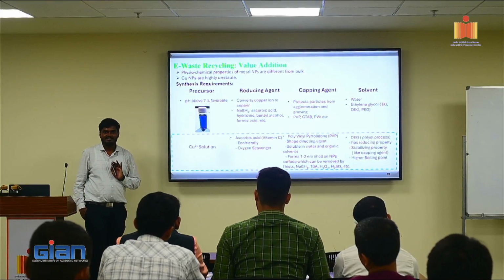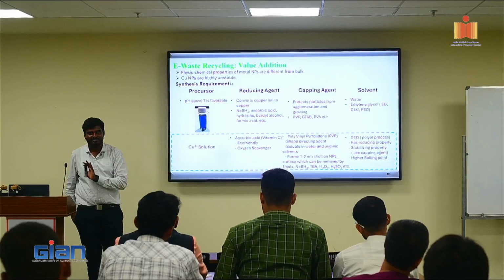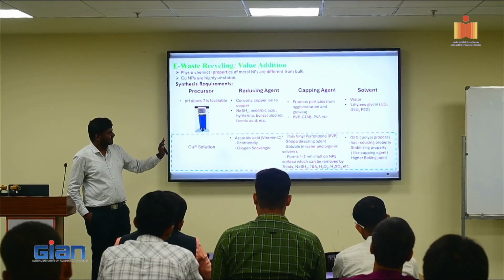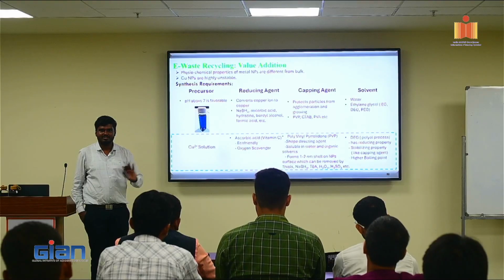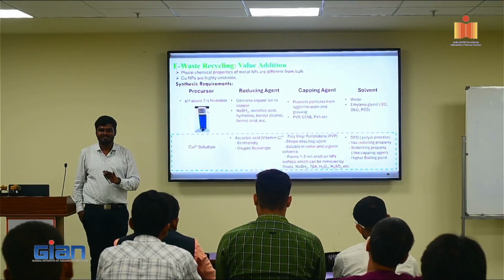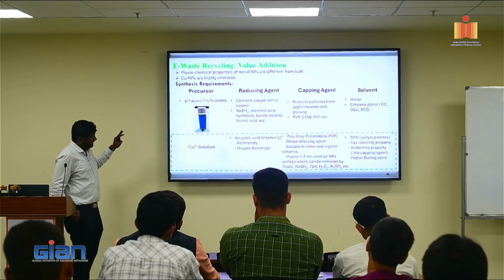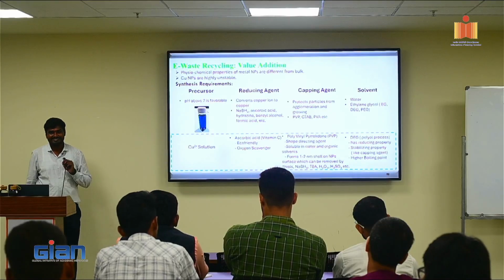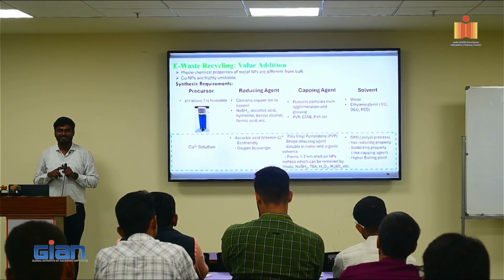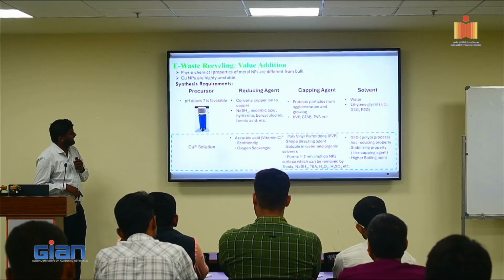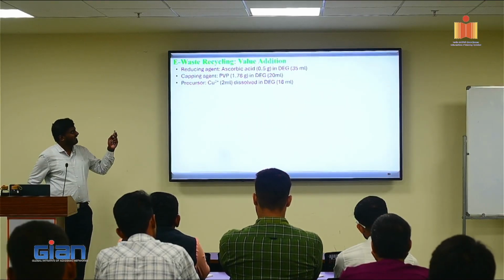The reason why I use diethylene glycol is the solubility of oxygen in diethylene glycol is very low compared to water. So if oxygen is less soluble, then there is no chance that copper will get oxidized. So I had to find out all this recipe. Once I found it, then I had to optimize the conditions. So again, I had to do some research where I optimized the conditions.